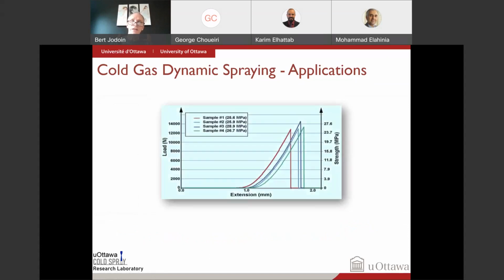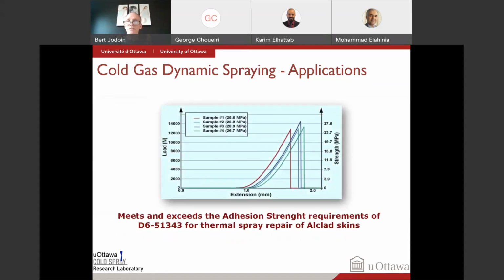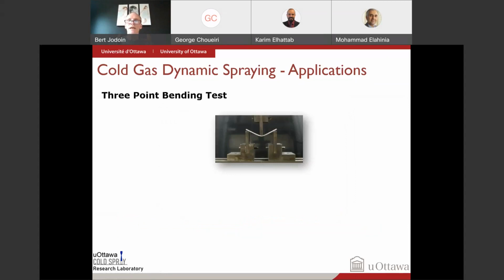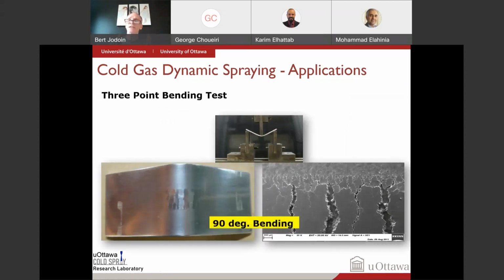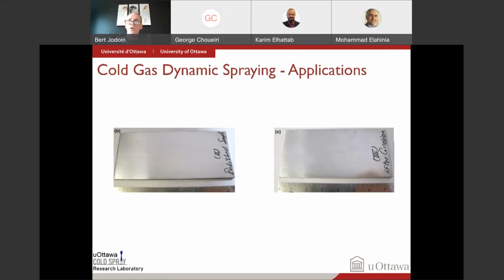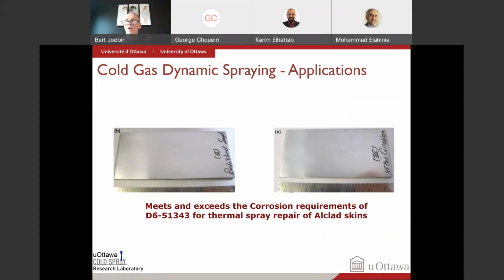So I'll just try to fly a little bit to demonstrate that we went to adhesion strength that were beyond what they were hoping for, expecting. And 3-point bending was to demonstrate that it doesn't delaminate. So it does crack, yes, but it doesn't delaminate, which is exactly what happens also when you have the pure Alclad thing there. And corrosion, we went under 5,000 hours of accelerated corrosion testing, and yes, it behaves as it's supposed to, so that's why they've adopted this.